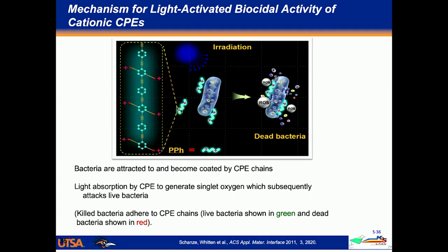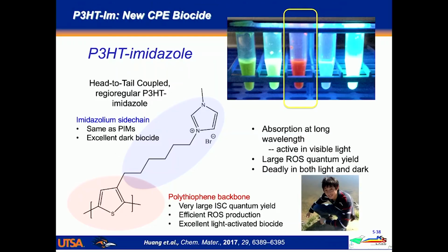This basically highlights the mechanism that we think is going on: you've got a positively charged polyelectrolyte, it interacts pretty strongly with the phospholipid membrane on the surface of the bacteria, and that brings the polyelectrolyte into close proximity. Light exposure generates reactive oxygen species, which then react with cellular components and inactivate the microbes pretty rapidly.